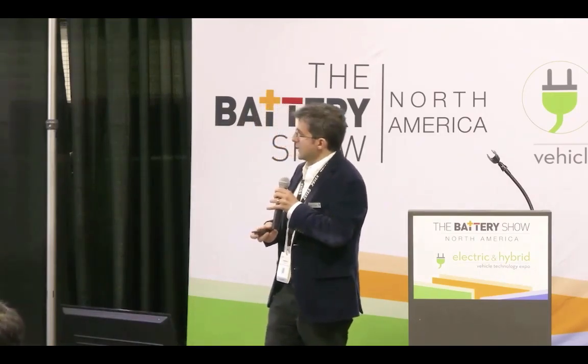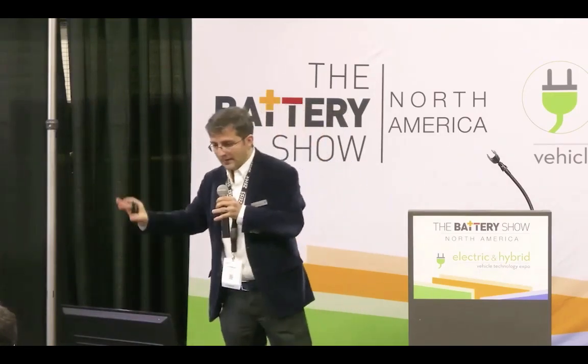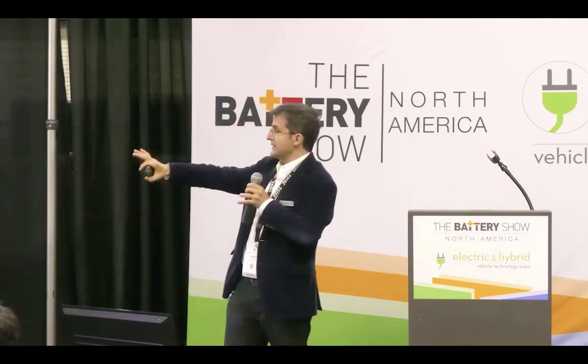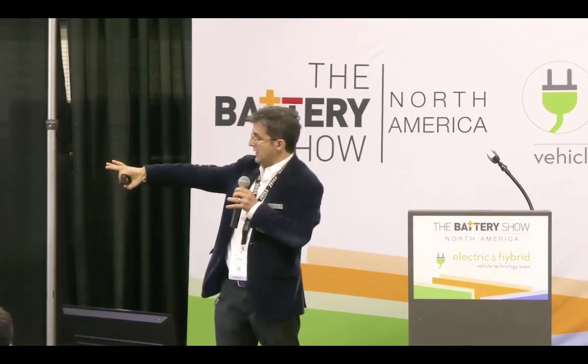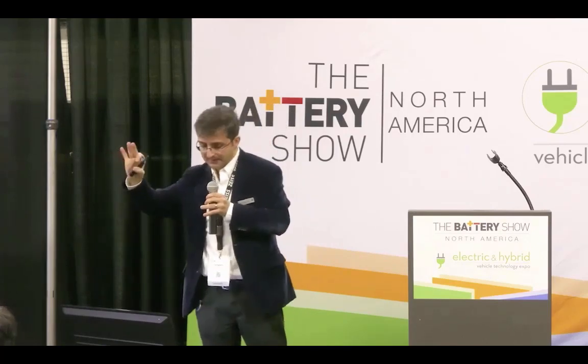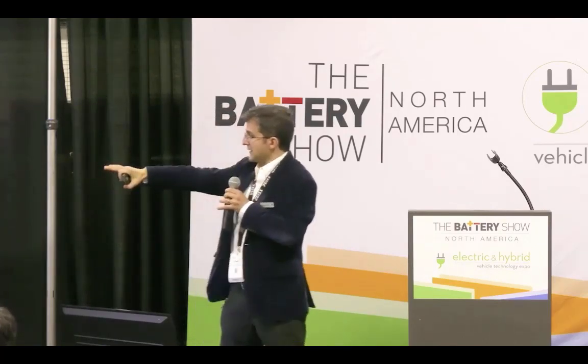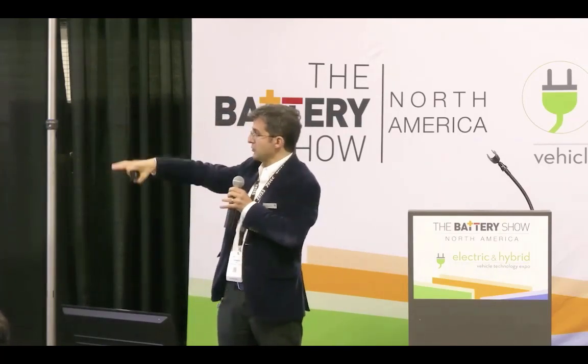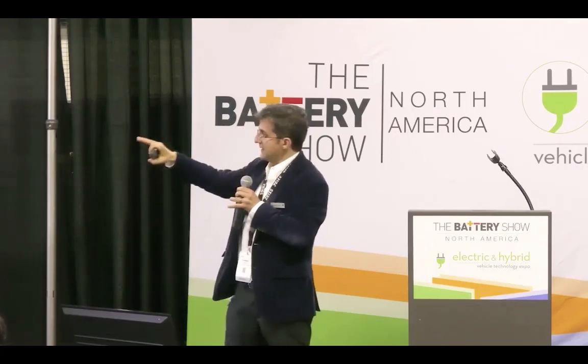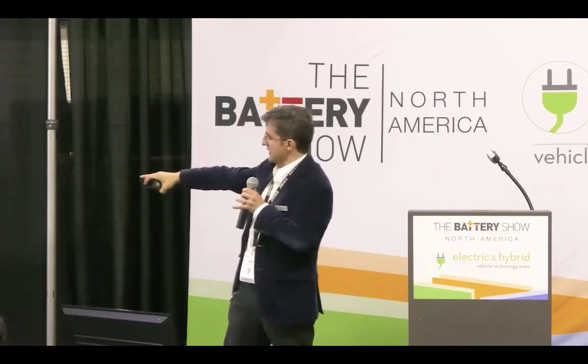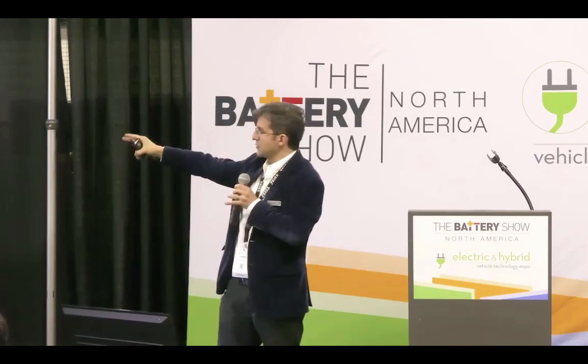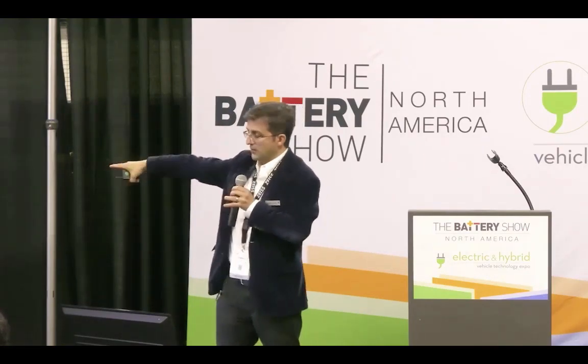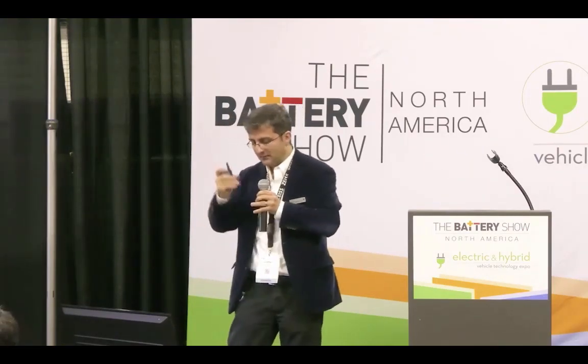Let me see if I can show you the workflow. It's summarized here. Basically, you can collect... voxel size is a measure of resolution. You can get a general overview of the full battery and then zoom in on the different regions until you get 2 micrometer voxel size for the full scan of this region at a higher magnification.